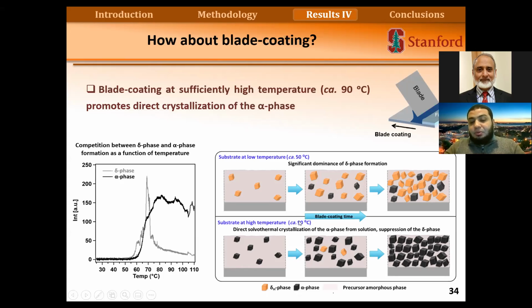But if we use blade coating at higher temperatures, we can get rid of the delta phase and we form directly the alpha phase. We found that we see some delta phase that forms and disappears very quickly, but at 90 degrees we can get the final product directly without having a second step of annealing. And I think this was very beneficial because here the temperature of blade coating was 90 degrees, but when we do annealing after spin coating, we need higher temperatures. So when we do blade coating, we can also use a lower temperature in order to process the film, and we can do only one step without doing spin coating and then annealing. We can just do one blade coating, and in a few seconds we form the final product directly if we have sufficiently high temperature.